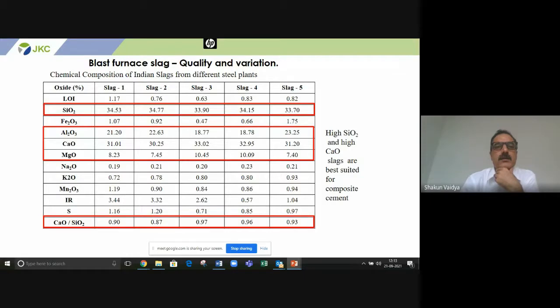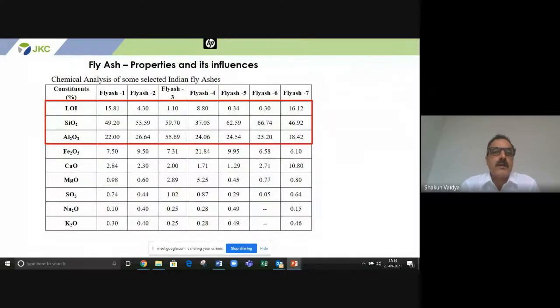Now blast furnace slag, granulated blast furnace slag, the quality and the variation. As I told you, these are tests conducted on various slags from different sources. But yes, it has to be rich in lime and silica, and the ratio of lime to silica should ideally be more than 0.9. This sort of slag is suitable for blending. Then fly ash has to be rich in silica. These are the various fly ashes where tests were conducted. It varies from around 40 to 60%. The higher the silica content, the more reactive the fly ash is. So it has to be rich in silica as well as alumina.